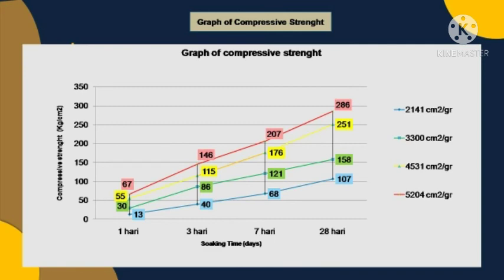One of them is Blaine 2141 square centimeters per gram. At 1 day, the compressive strength value obtained is 13 kilograms per square centimeter. 3 days obtain 40 kilograms per square centimeter. 7 days obtain 68 kilograms per square centimeter. And at the age of 28 days obtained 107 kilograms per square centimeter.